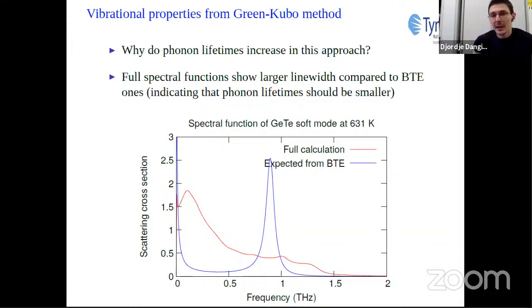Intuitively, it does not. And if we look at this phonon spectral function, we can see that the Boltzmann transport equation spectral function has a smaller line width than the Green-Kubo spectral function. This means that one should expect higher phonon lifetimes from the Boltzmann transport equation than from the Green-Kubo, which is not in accordance with the previous picture.